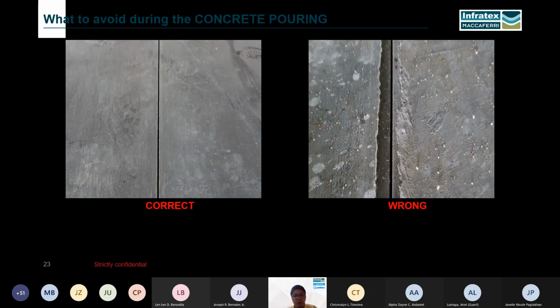So this would be an example of a nicely prepared or leveled concrete on the joints top strip. And in this case, wherein the concrete overflowed on the top strip, it normally causes excessive dusting and unlevelness on the joints, which is a common cause of safety issues and forklift accidents. So make sure to avoid overflowing of your concrete on the top strip level.